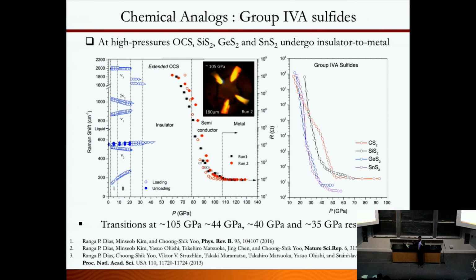What if you remove one sulfur and add oxygen? You make an intermediate state of carbon dioxide and OCS. So how is that going to behave? What is the role of oxygen and sulfur? Why is CO2 not a metal under pressure? We put it into a pressure of around 250 GPa. It's transparent, it's an insulator. But carbon disulfide at around 50 GPa becomes a metal, but not carbon dioxide.